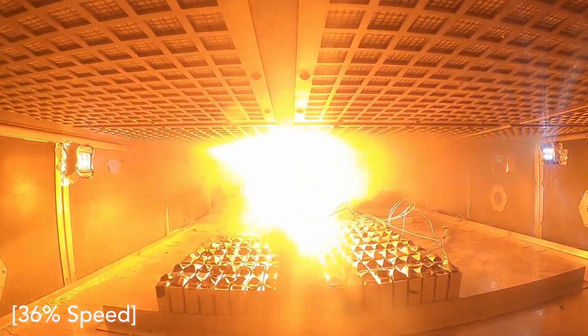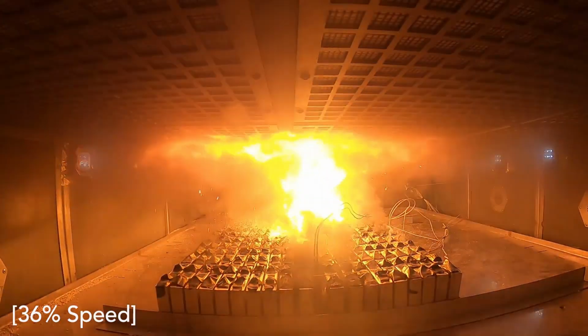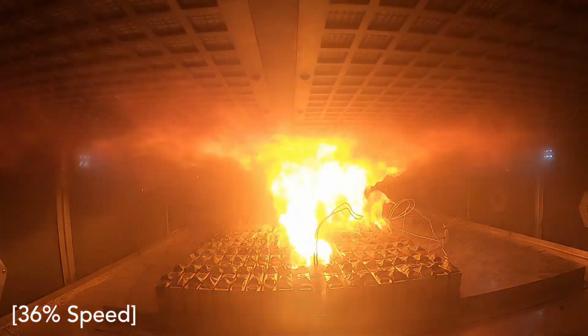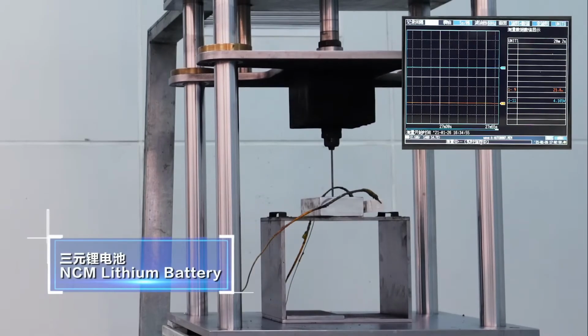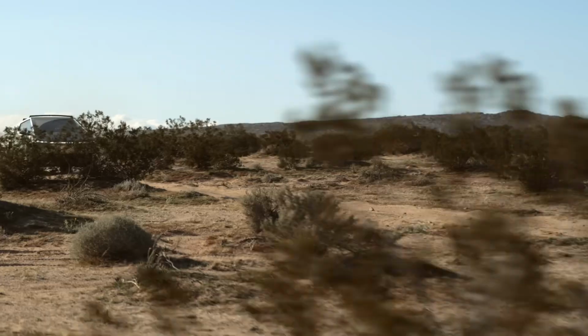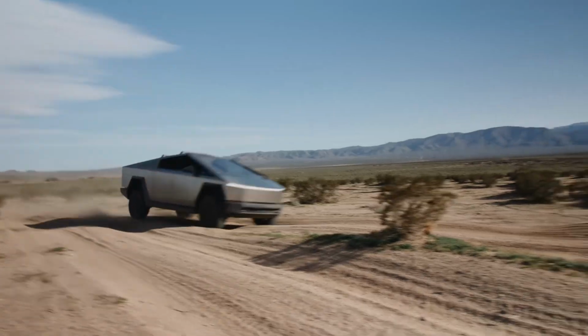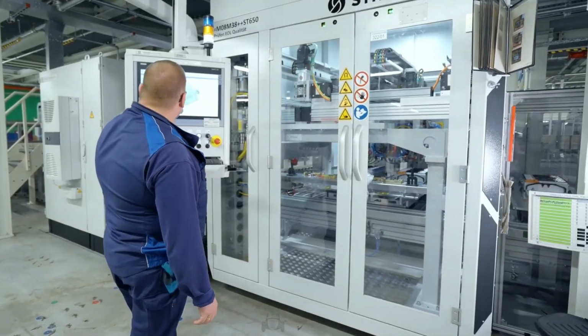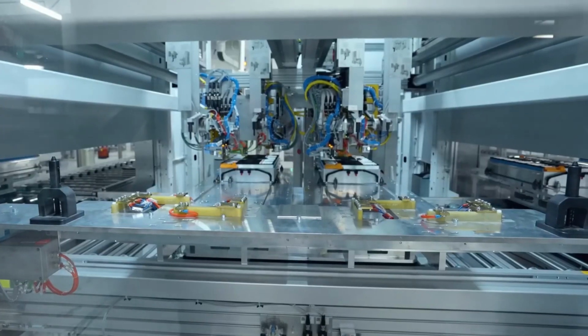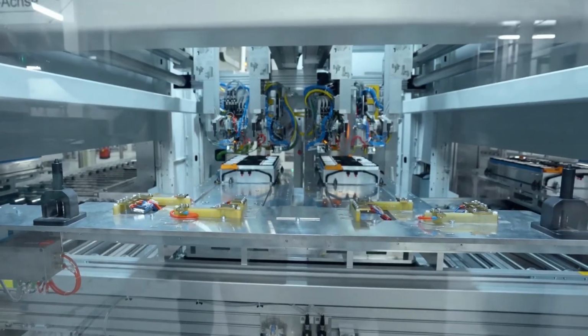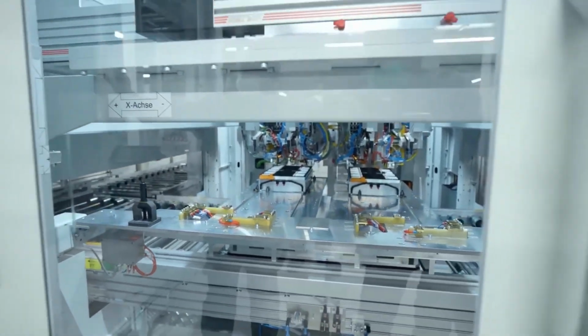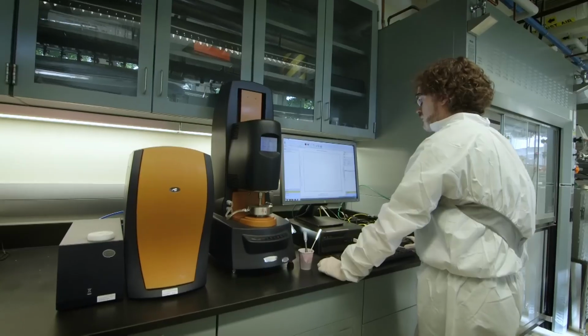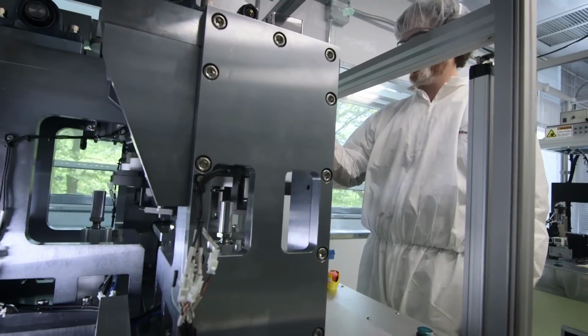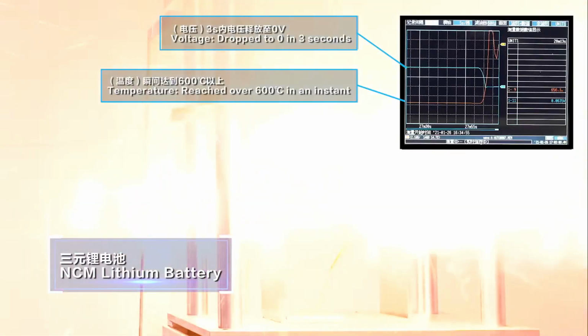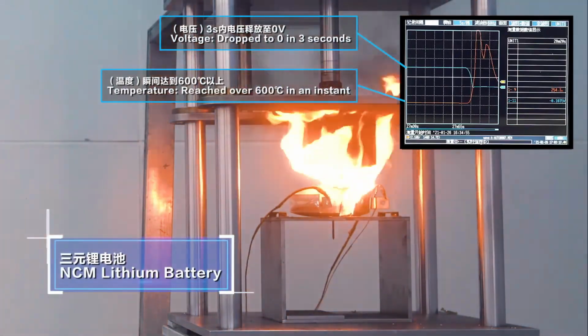The testing phase is where the battery's mettle is truly put to the test. In addition to extreme temperature and puncture tests, batteries are subjected to vibration tests that simulate the rigors of driving on rough roads. They're also tested for cycle life, which involves charging and discharging the battery thousands of times to see how it holds up over time. Some factories even use accelerated aging tests, where batteries are exposed to high temperatures and voltages to simulate years of use in just a few weeks.